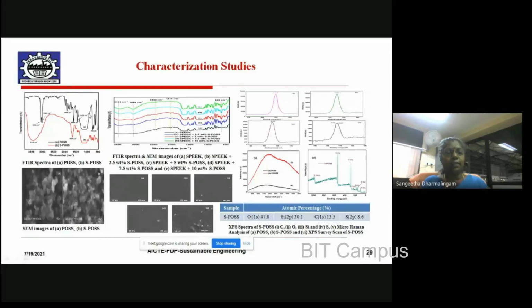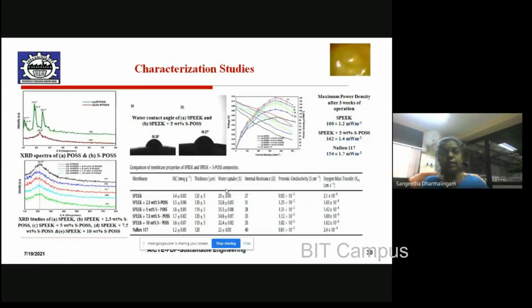So these are all the FTIR results which confirm the functionality of the polymer membranes that are developed, the functionality of the nanofillers, and these are all your composite materials. This is your POSS, sulfonated POSS, and these are SEM images of the caged structured POSS materials. And after sulfonation, how do they appear? And these are all the SEM photographs of the membranes, and these characterizations confirm the presence of your sulfur, your silicon, your POSS content, and everything. And finally, we also did some XRD to compare the crystallinity and the reduction in crystallinity, hydrophilic nature, and ion exchange capacity. This ion exchange capacity, your water uptake capacity, resistance, conductivity of the membrane, and the oxygen mass transfer is another very important parameter.